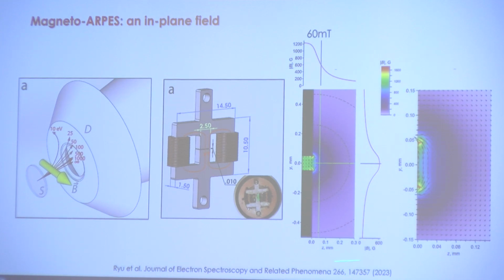this is a totally independent effort at implementing magneto-ARPES. The phrase magneto-ARPES is really from Eli Rotenberg, who's at the Advanced Light Source. And this is their device, which is a way to apply in-plane magnetic field at the sample location. They make this yoke shape with a cut. This is I think an iron core, and then there's a cut in the middle, and this is where the sample will be glued. They did simulations of how high a field they can achieve at the sample location, and according to this construct, it is 60 millitesla at the location of the sample.